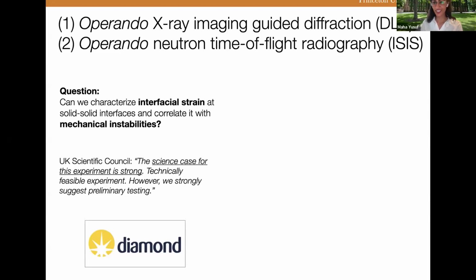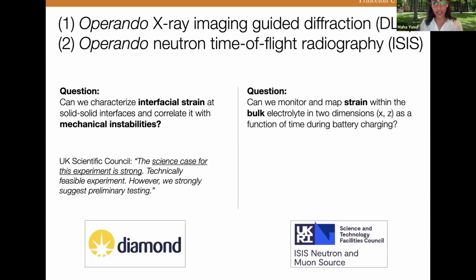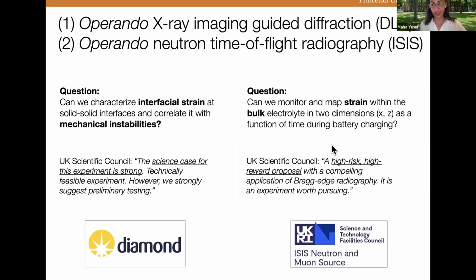And per the UK Scientific Council, this experiment is very, very challenging. In fact, I just finished this experiment three weeks ago here at Diamond Light Source. And the second technique that I'm developing is operando neutron time of flight radiography. With this technique, I want to investigate, can we monitor and map strain within the bulk electrolyte, not at an interface, but in the bulk electrolyte, in 2D as a function of time as the battery is cycling? And again, per the Scientific Council, this is a very high risk and high reward experiment.